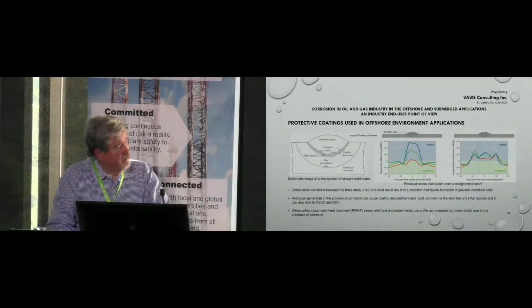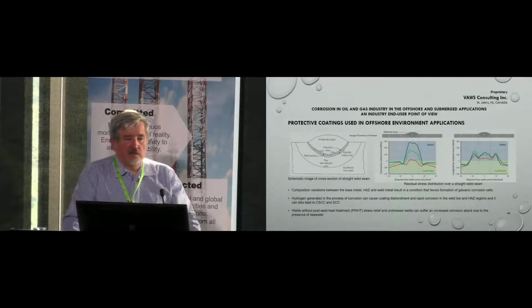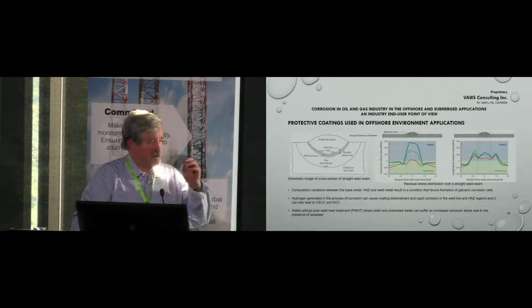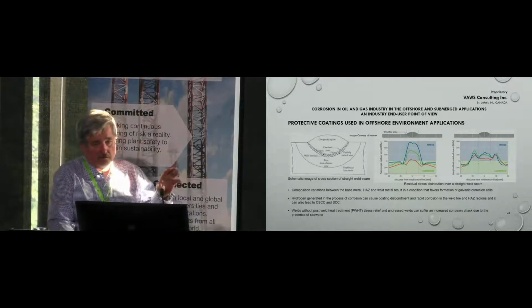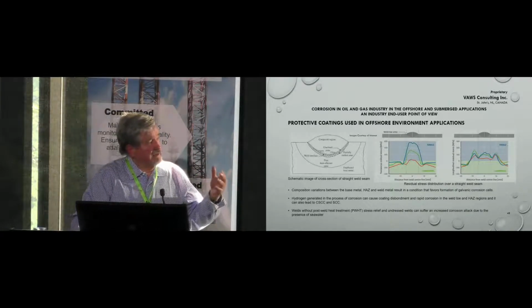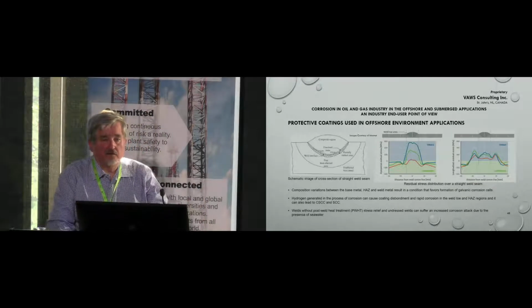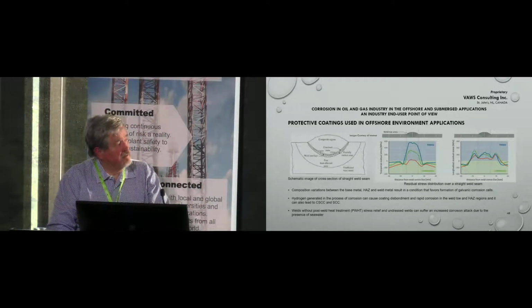Welding, very important thing in offshore. As you see on the picture on the right, the weld consists of numerous layers: heat-affected zone, mixed layer, a pure weld, a pure metal, and all these have certain energy in it. As I showed originally, all this energy is a mirror for the corrosion. So the weld can corrode on itself because of the different energies in the metal.